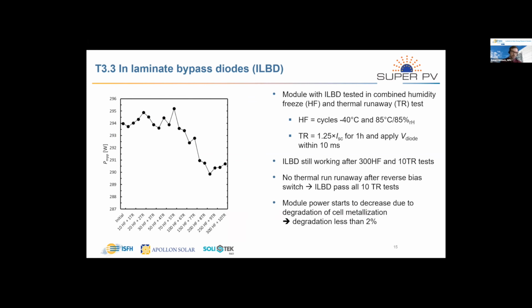This is shown here. The module power output of one module with this in-laminate bypass diode, and we tested in a combined test of humidity freeze and thermal runaways. The humidity freeze test is according to the IEC 61215 standard, where you cycle between -40 degrees and 85 degrees and 85% relative humidity. And then we also apply a thermal runaway test, where you apply 1.25 times the short circuit current of the module for 1 hour, and then immediately switch after this 1 hour to the diode voltage within 10 milliseconds.